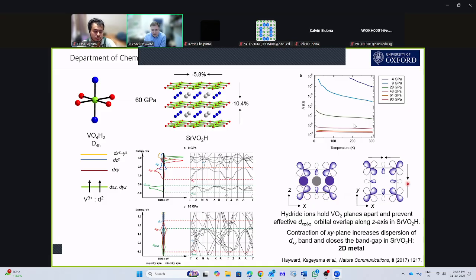The band gap actually gets closed by the XY direction contracting, and that then broadens this XY band, which comes down to close the band gap. And as a consequence, what we find is that the band gap still exists in the Z direction of our material. And so we end up with a metallic system that has very two-dimensional conductivity. The conductivity in the XY plane is much, much greater than in the Z direction.